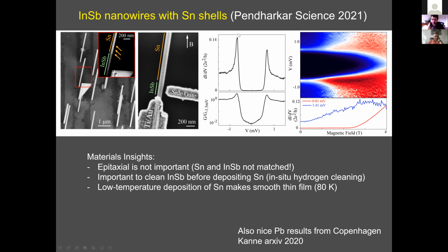And it shows good results. It shows this very clear induced gap when we tunnel into this tin. This is a log scale, so suppression of conductance is 2 orders of magnitude, which is sort of state of the art. And this gap survives to pretty high fields. Here we have 4 Tesla before it closes. That's because the film is very thin, so it's important to have a thin film. And we also saw 2e tunneling in this tin, which has not been seen in anything but aluminum until we did this in tin, which is important for topological qubits.